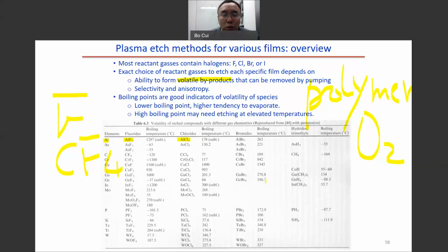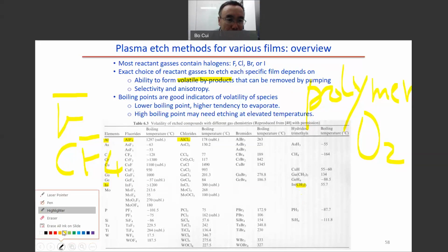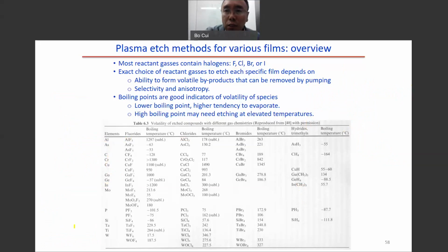So which material to etch and which gas to use depends on whether you form a volatile product or not. Now let's look at other materials. Say if you want to etch away indium, we know indium chloride is hard to volatilize, but methane gas can form In(CH3)3. That means you can etch away the indium using methane gas.